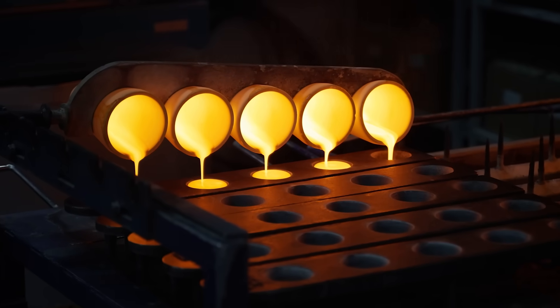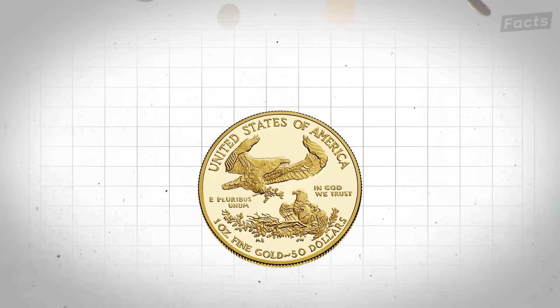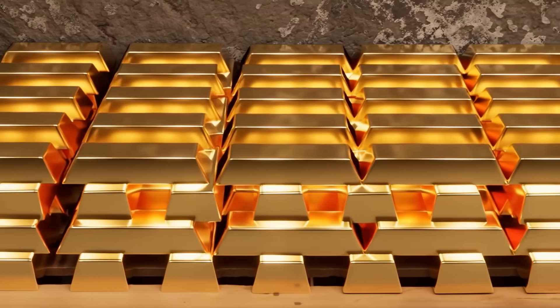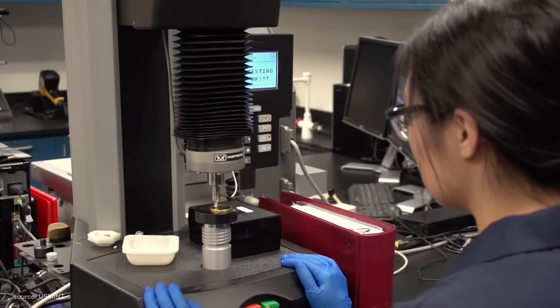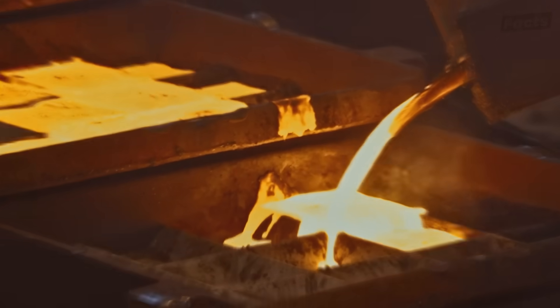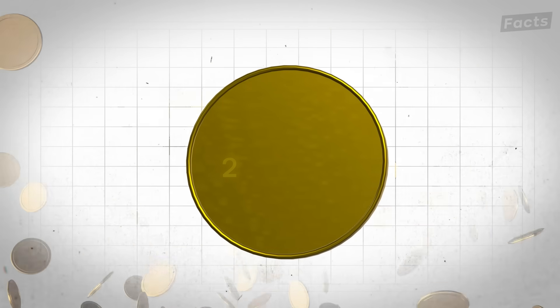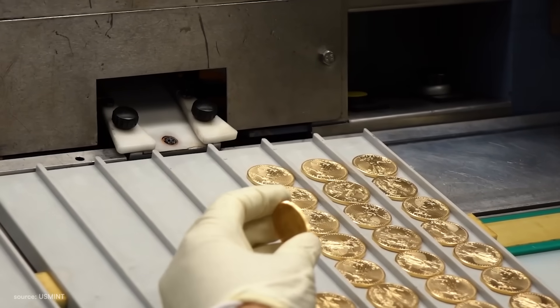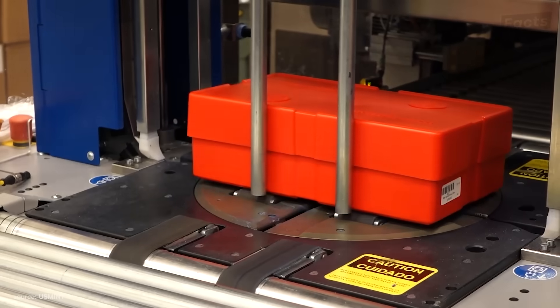But that gold might not go out as a bar — still more fire could be waiting for it. These are gold coins coming from the U.S. Mint. They're legal tender under the Gold Bullion Coin Act of 1985, but it's a long journey to get them. The Mint buys gold bars from the open market, verifies their purity and authenticity, then melts and alloys them to exact specifications: 91.67% gold, 3% silver, and 5.33% copper — a durable 22 carats. Once weighed, the coins are shaped into blanks, blank disks ready for their final designs, then go through the same striking process used for regular currency before being shipped to authorized dealers.